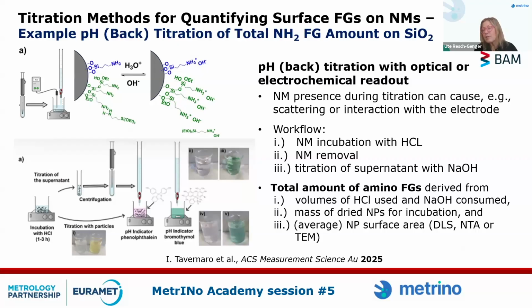And we decided to go for back titration. The reason for this was when you do optical measurements and you have a scattering nanoparticle dispersion, this makes it really difficult to detect a pH change with the eye or even with a smartphone camera. Think about 50 nanometer sized silica particles, they show up as a milky solution. So even with a strongly colored indicator dye, you don't have a chance. And they can also penetrate a pH electrode and mess up your electrode.